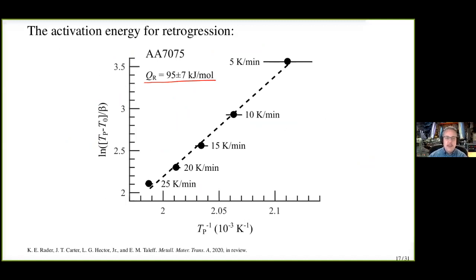If zinc is the rate controlling diffusive species, this activation energy is about what we would expect. But moreover, we get a nice, pretty straight line, which tells us that the simple model we assumed of a simple thermally activated process is actually kind of okay. So the simple model seems to be sufficient to our needs, even though there may be more complexity going on. It looks like the more complex stuff is a second order effect.